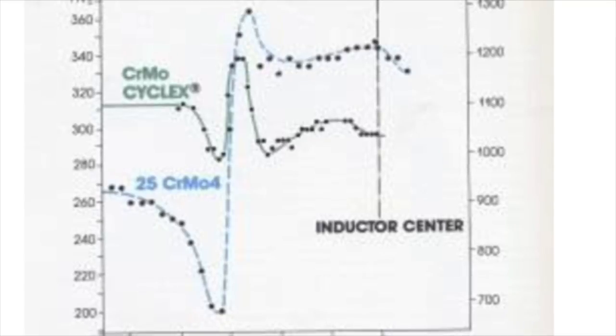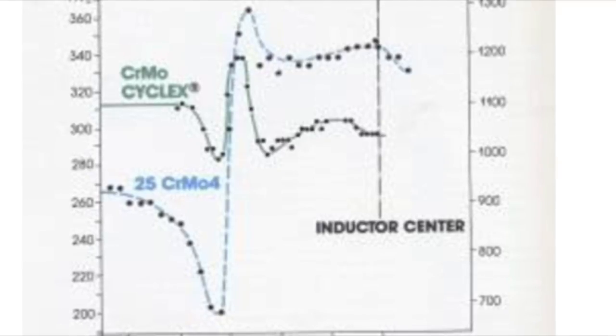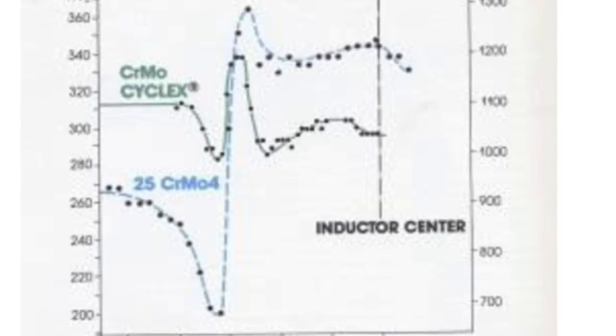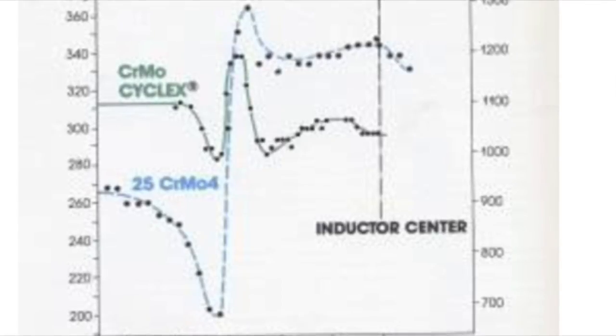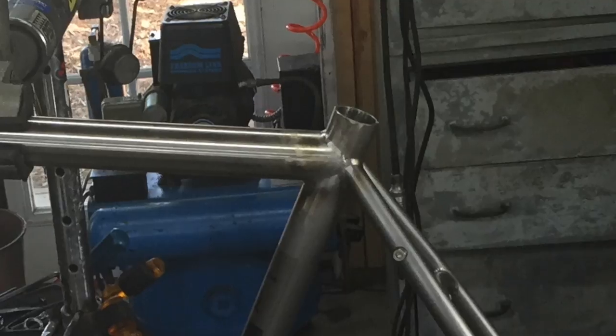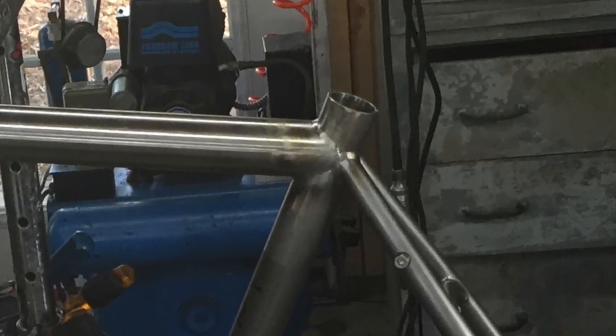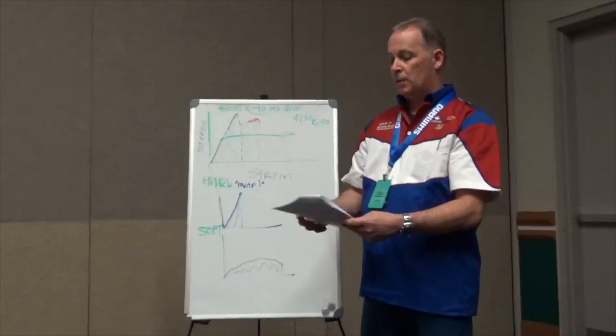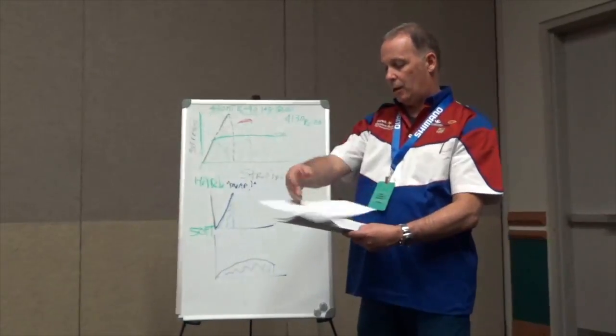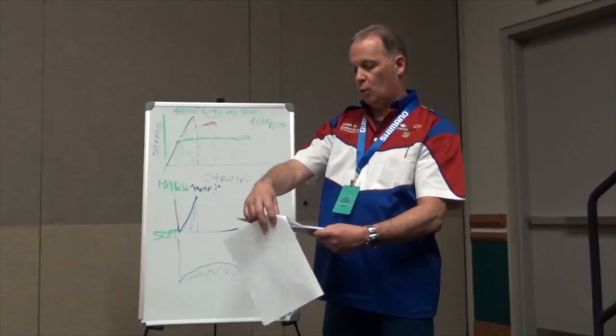So what this is trying to show you is when you TIG or braze, the material hardness changes, everybody knows about a heat affected zone, and that's really what this is showing. Where you see the lowest point where it's soft and where it starts to return, if you saw the blue lines on the TIG joint, that's about where those blue lines would appear. So that's kind of just a background on what we did.